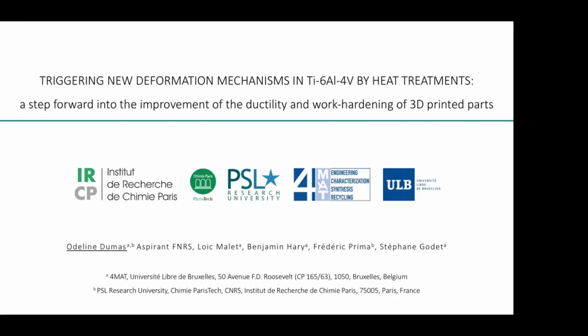And also maybe a last question: when you're finished reorienting, you have only one variant left. Then you expect the ductility is gone in that phase. Yes, in fact, if we look at the Schmid factor, we have a very precise scenario because we have a Schmid factor which is very low for the basal plane and very high for the prismatic plane. So thanks to that, I thought, okay, maybe I can reorient and have very hard grains, for example. But it's not so clear because the CRSS of both basal and prismatic are quite the same in the martensite of Ti-6-4. So it's hard to say, but we think that in fact the ductility is decreasing. Yeah, I guess so.